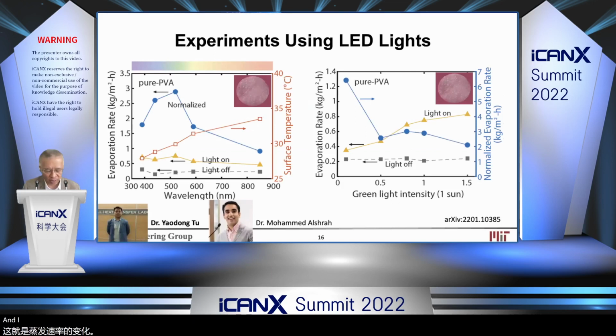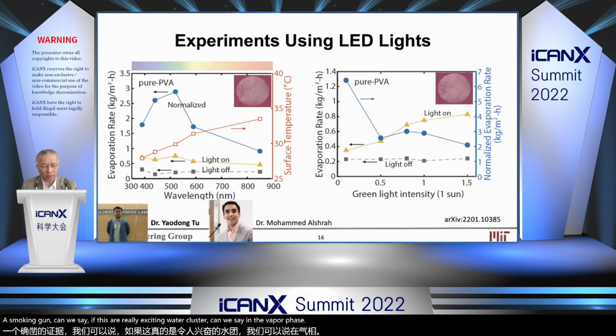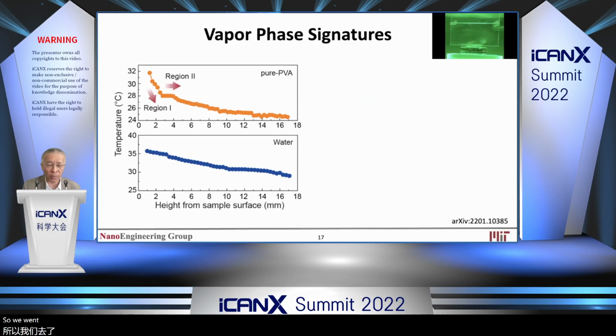And I, again, pushed Jiandong. I said, I want a smoking gun. If this is a really exciting water cluster, can we see it in the vapor phase? So we went to the vapor phase again, because in the vapor phase, we saw the flat temperature region two years before this. And in the pure PVA, we saw it again. You can see there is a flat temperature region. At the bottom is pure water, which never has that.